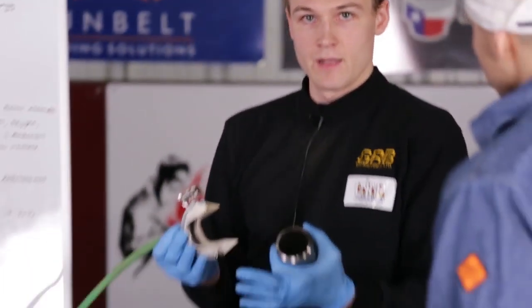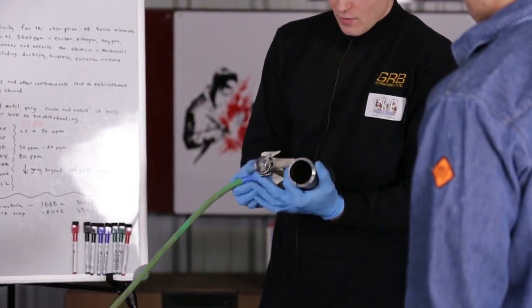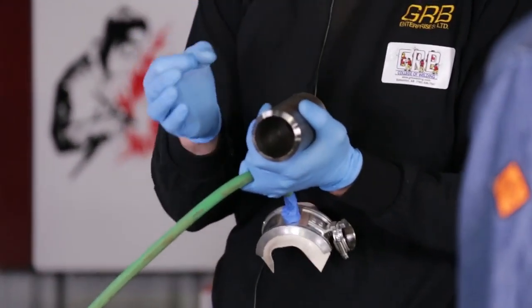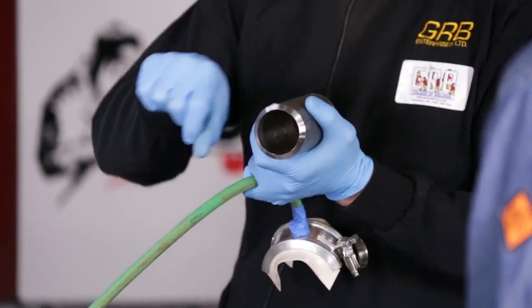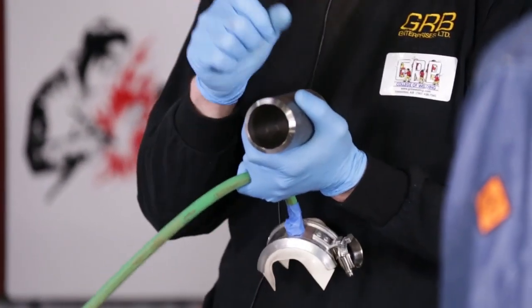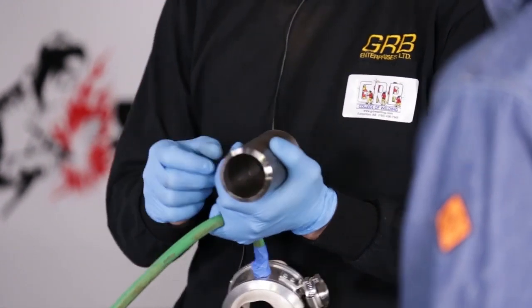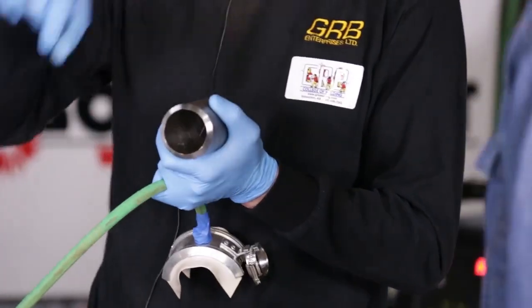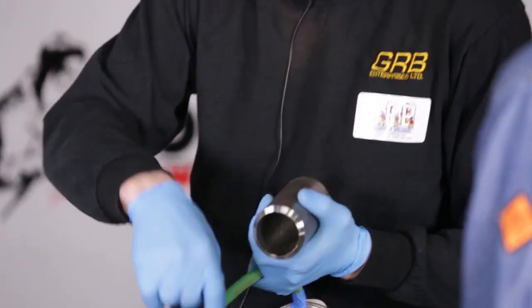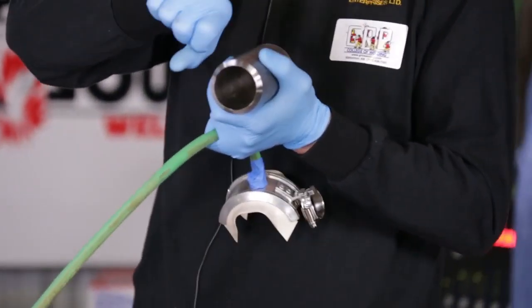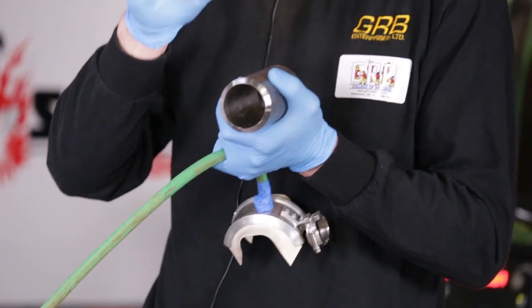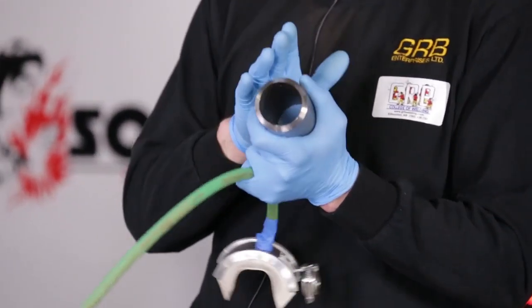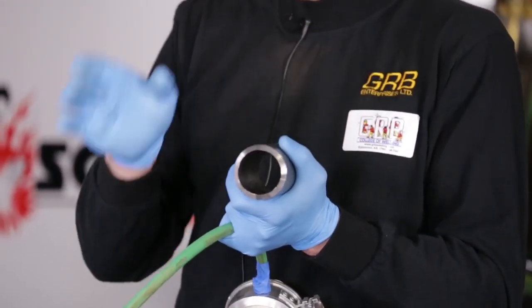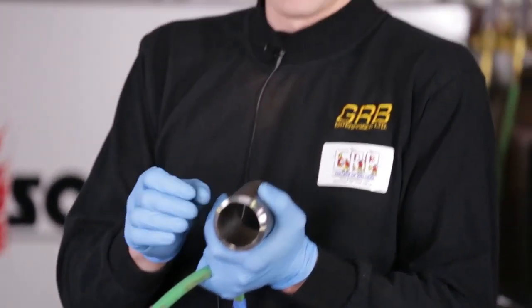Now I also want to mention that with titanium, another technique that Jerry at GRB College of Welding had taught me was that you can take a single individual ceramic cup, you could make one ripple at a time, and you can protect that for about 6, 7, 8 seconds. That will protect it away from the atmosphere. Then you can move to the leading edge and make another ripple with a surge of current, drop the current, and protect that ripple for about 8 seconds. Around 6 seconds, the redness of the color will dissipate and then it'll turn silver. It takes about another 2 seconds for it to be completely silver. It is not hot enough to interact with the atmosphere to form oxides.